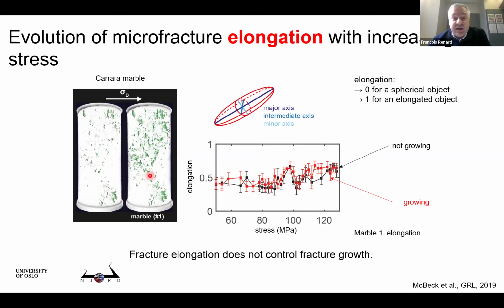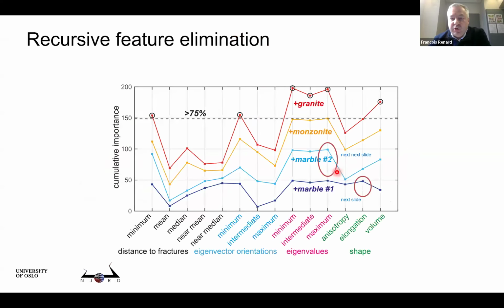So first, let's take all the fractures and look at the elongation of the fracture as a function of stress. So the sample will fail here. For the fractures that grow and the fractures that do not grow, what we see is that the elongation is more or less the same. So if we come back here, elongation is not a very important parameter that controls fracture growth. But now let's look at this one.